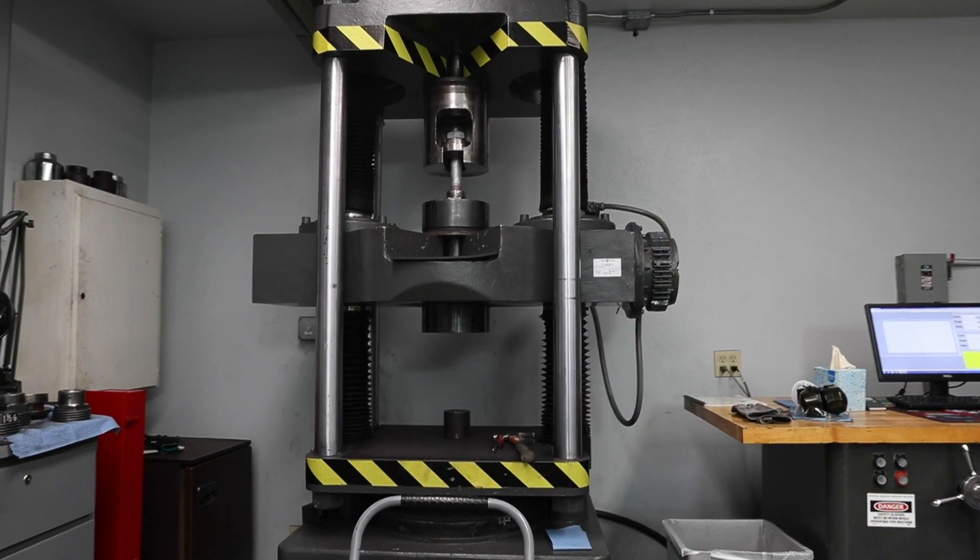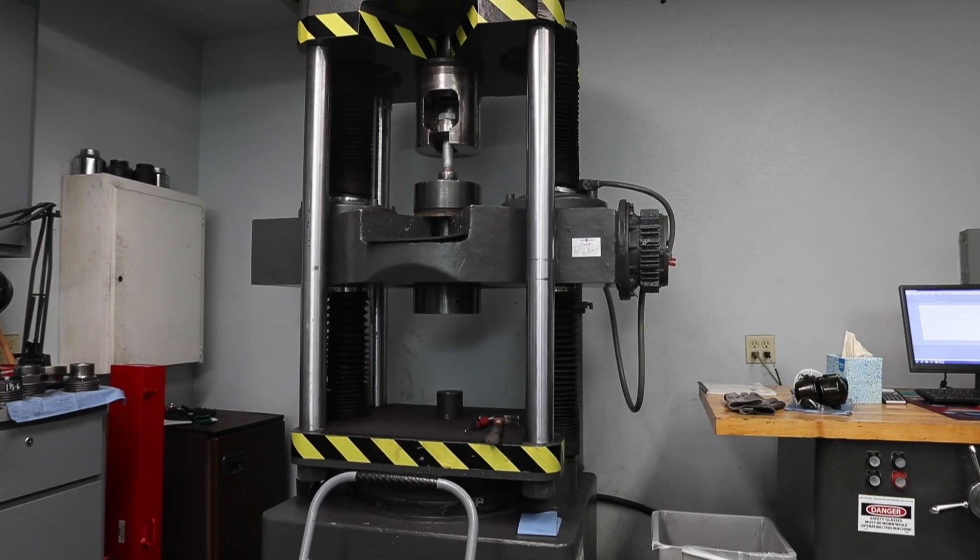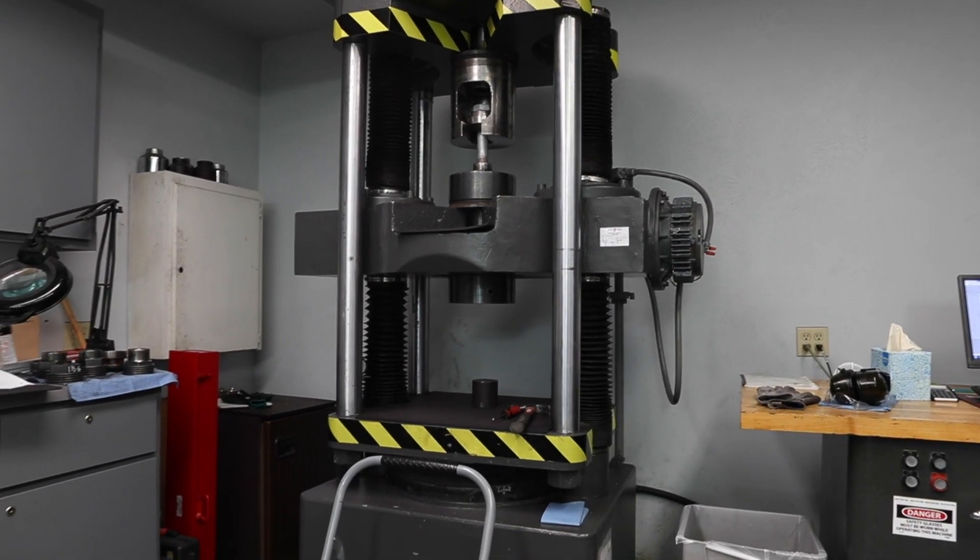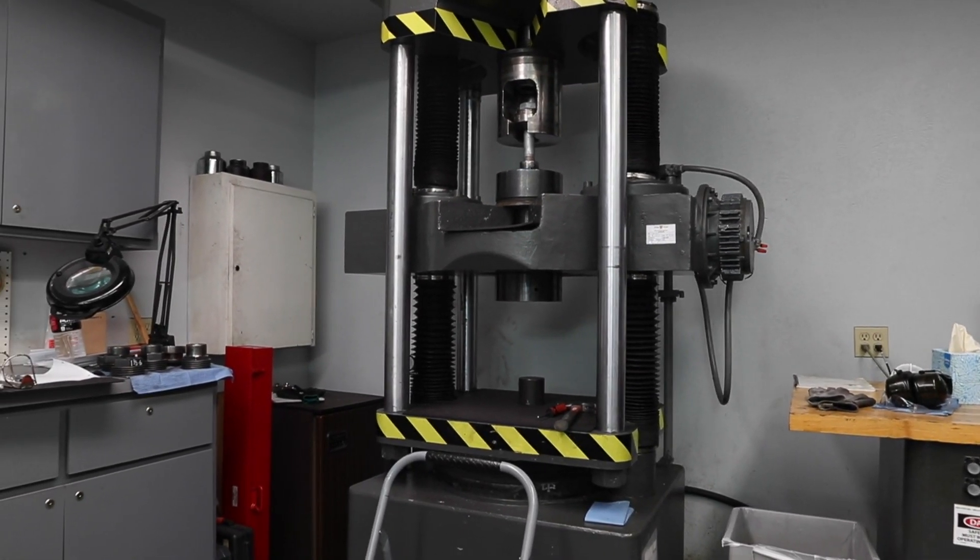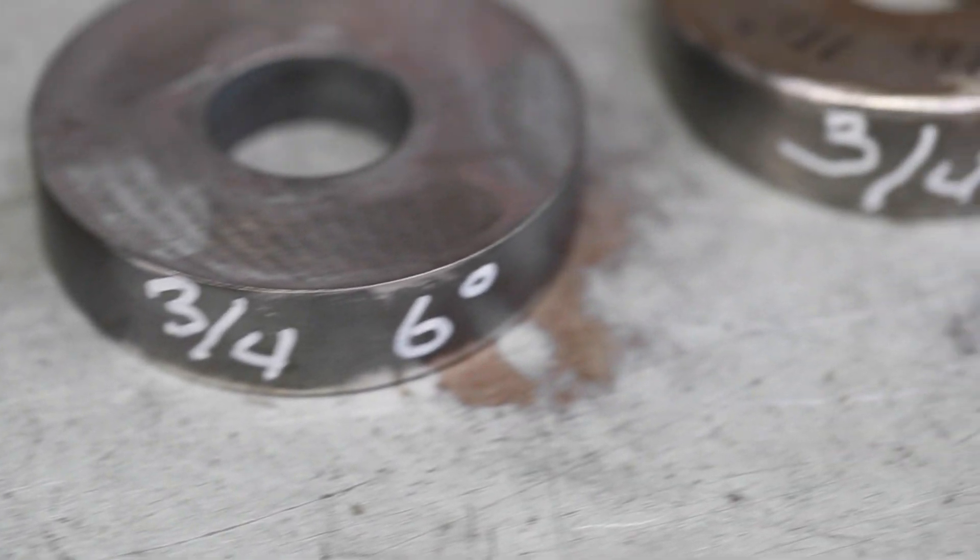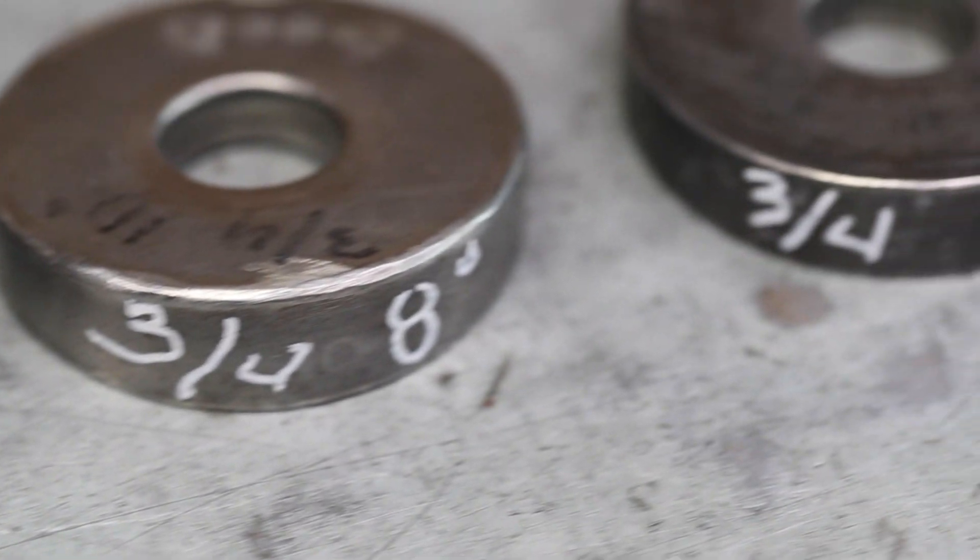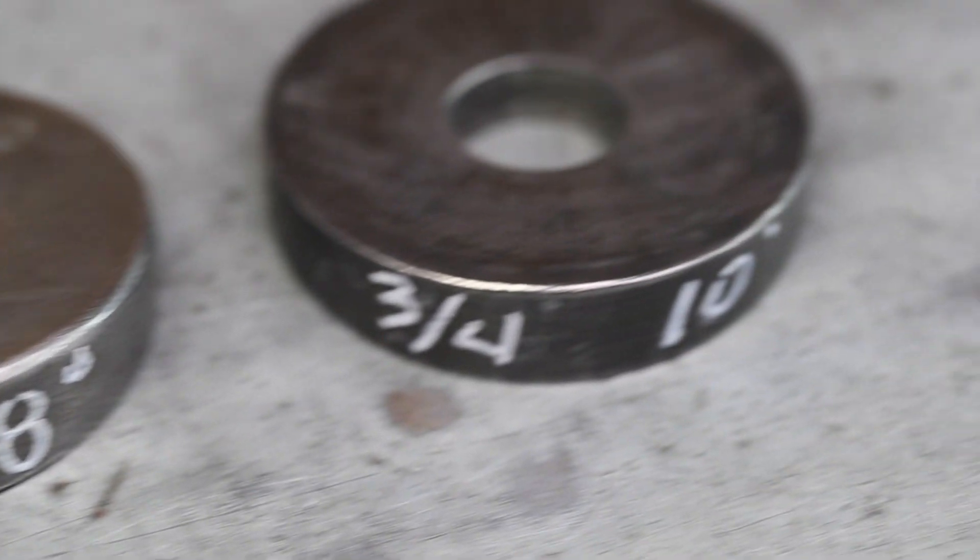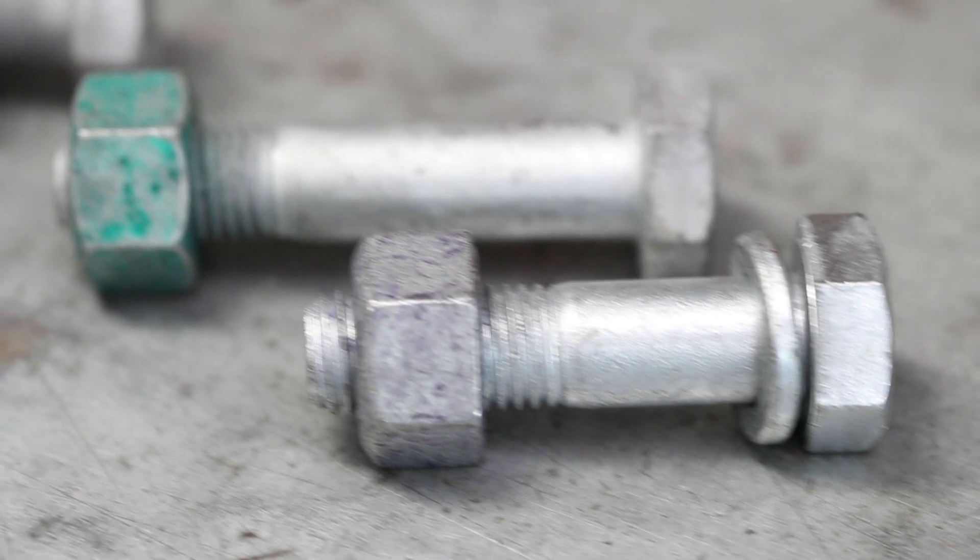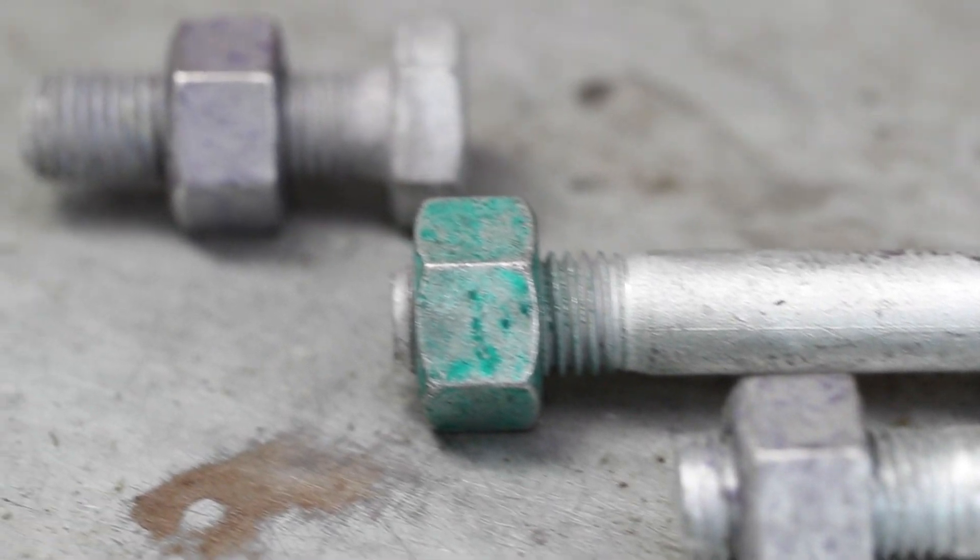The correct wedge angle must be used. The standard test angles are 4, 6, 8, and 10 degrees. The selected angle depends on the specification, the bolt's grade, the bolt's diameter, and the distance from the thread to the underside of the head.